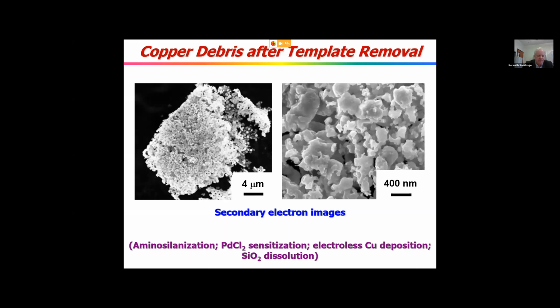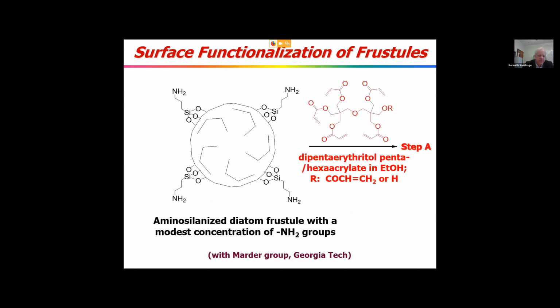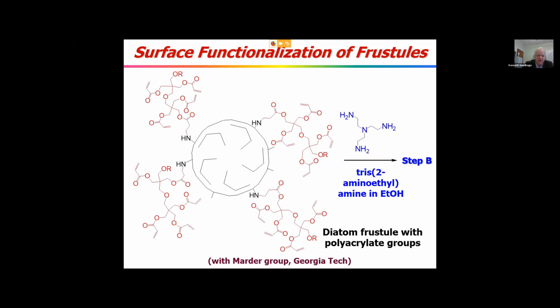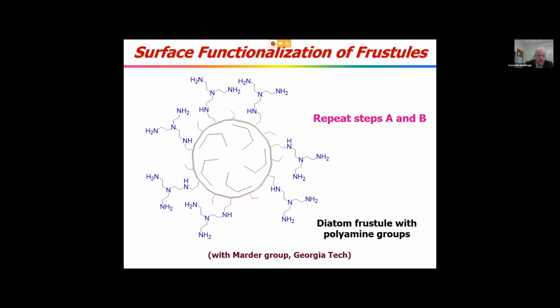You again can put amines on the surface through the silanization process I just mentioned, but you can amplify those amines. And so the idea is to take a multi-acrylate molecule like dipentaerythritol penta-/hexaacrylate with 5 or 6 acrylate groups. Any one of those can react with the amines to covalently bond. And the remaining 5 or so acrylate groups can react with a polyamine like trisaminoethylamine. Any one of the amines can react with any of the acrylates. And you can go back and forth between acrylate amine, and really dramatically amplify the amine density on the surface to capture more catalyst to get a better coating.